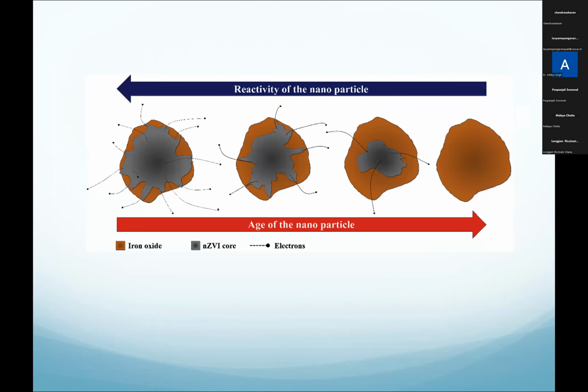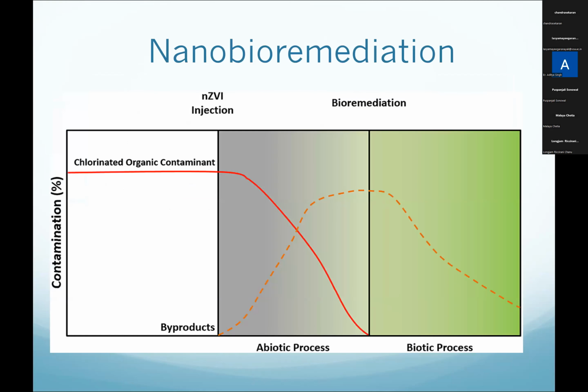Now, what happens is, with the age of the nanoparticles, I told you, the reactivity goes down. The particles' reactivity goes down with the age, and reactivity decreases when they get oxidized. So it's very important to make sure that we deliver it quickly when these nanoparticles are active. You don't want them to be passivated or oxidized under these conditions.